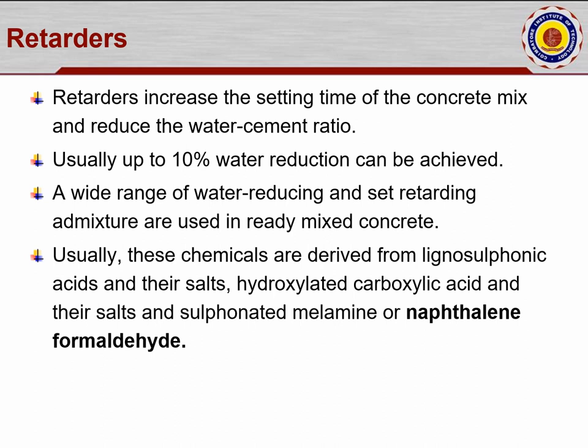A wide range of water-reducing and set-retarding admixtures are used in ready-mix concrete. For example, if an RMC plant is on the outskirts of the city and the concrete destination is in the city center, it may take nearly 45 minutes of travel time. In such cases, a retarder is added at the advisable level so that the concrete does not start setting during that 45-minute transport period.